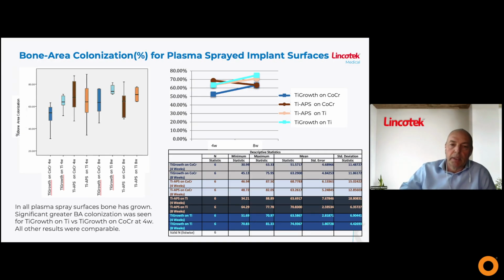Next, please. The bone area colonization is really important. The color code is exactly the same as seen before. Here the point was to show that even starting with large pores, the bone is able to colonize far away from the surface into those large pores. This colonization is higher at 4 weeks for TiGrowth on titanium, whereas there is no statistical difference at 8 weeks.